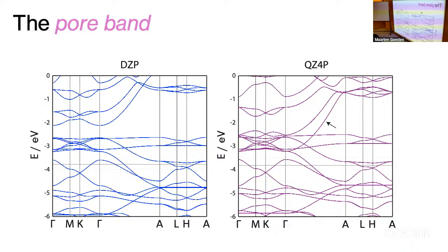And this is this special band that I showed, which was printed in blue a few slides ago. So that band, this is a Slater type orbital basis set. Those are like Gaussian functions, atomic orbitals, not plane waves. This is double zeta, it means smaller. This is quadruple zeta, it means more functions. What we see here is not only that this band becomes much stabilized, but there's actually a band here which completely vanishes at a smaller basis set. So the band is absolutely not reproduced. And this is as big as it gets. Quadruple zeta with Slaters is insanely big. We're looking at many, many functions.